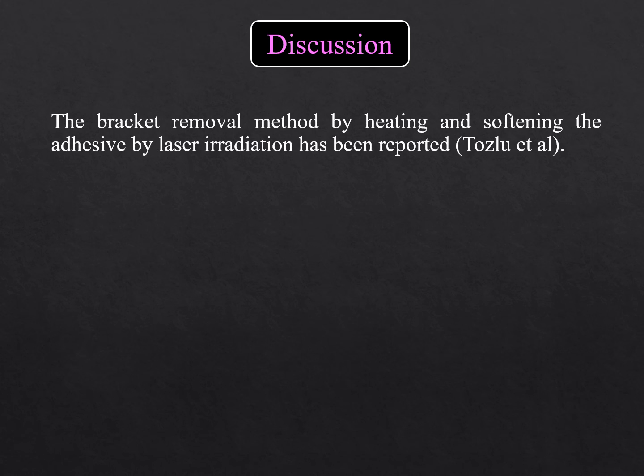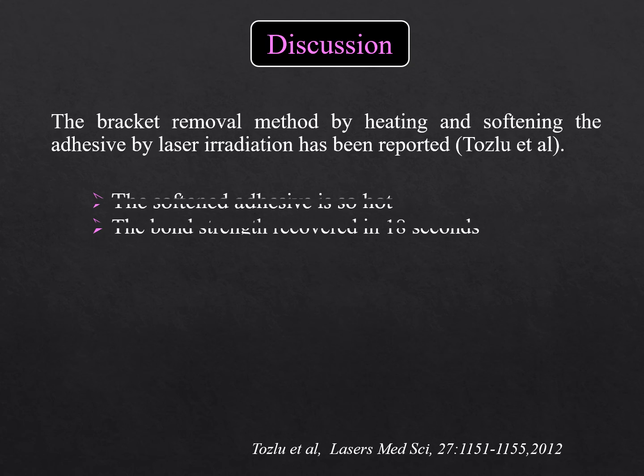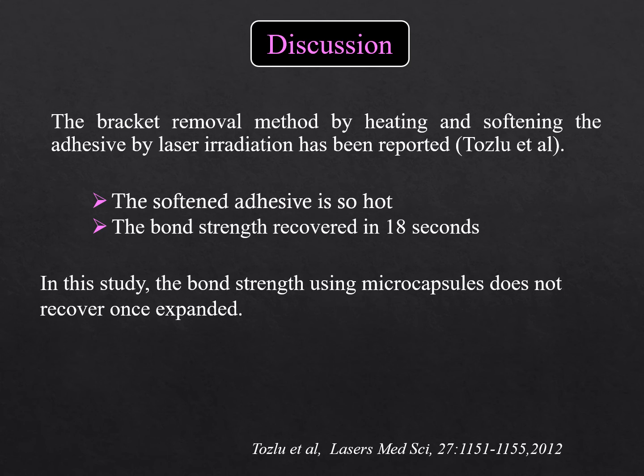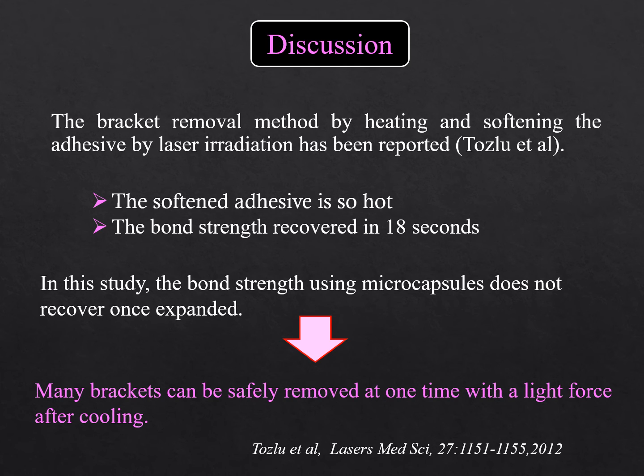The bracket removal method by heating and softening the adhesive by laser irradiation has been reported. But this operation is very dangerous because the softened adhesive is so hot. Furthermore, the reduced bond strength recovered in 18 seconds. In this study, the bond strength using microcapsules does not recover once expanded. Then, many brackets can be safely removed at one time with a light force after cooling.